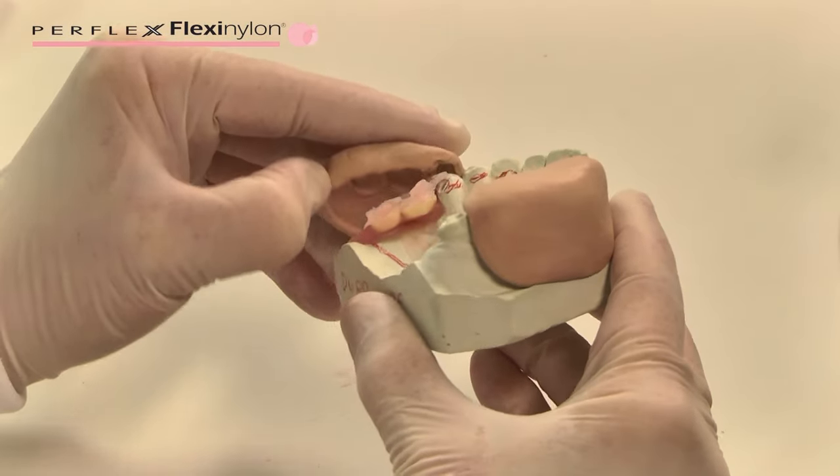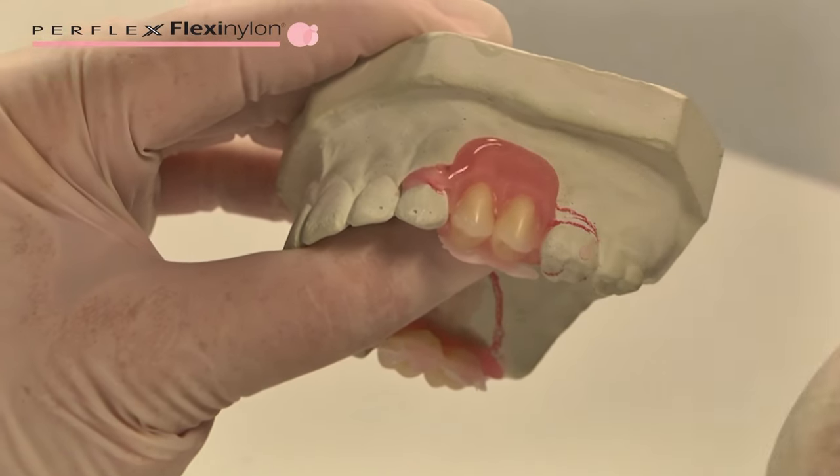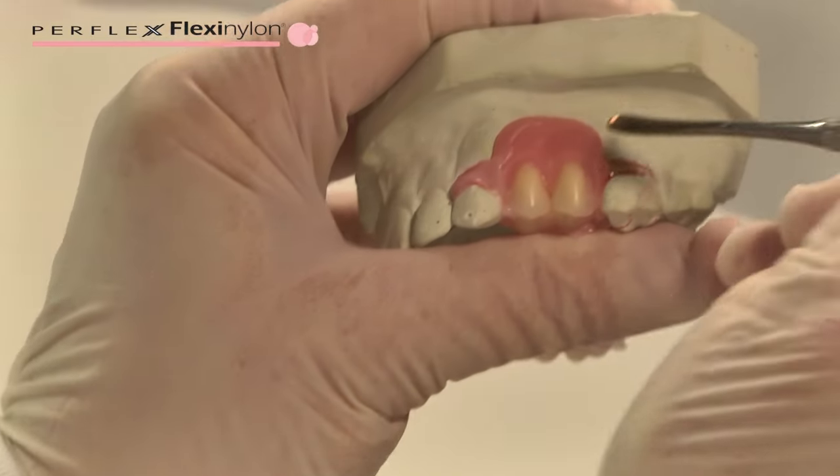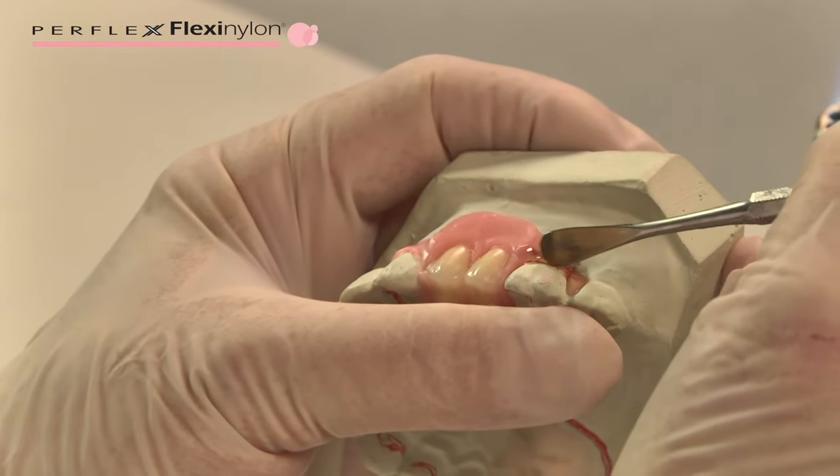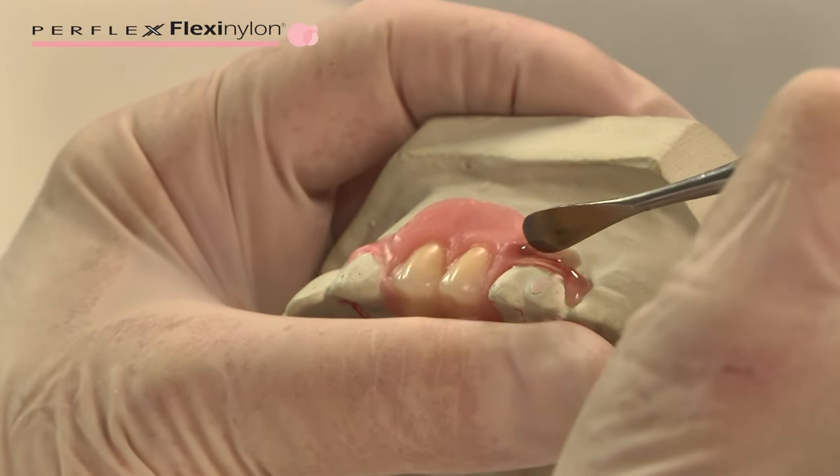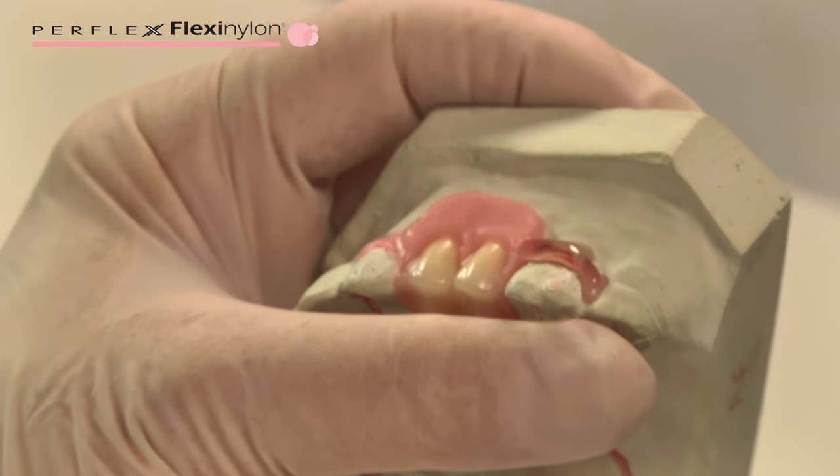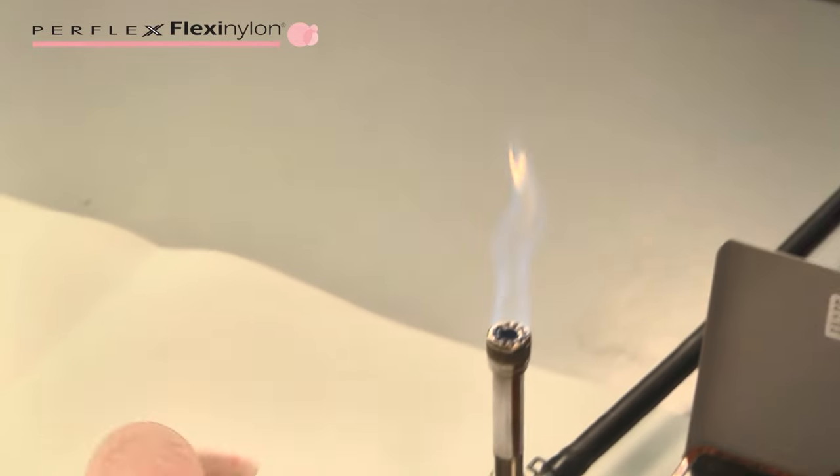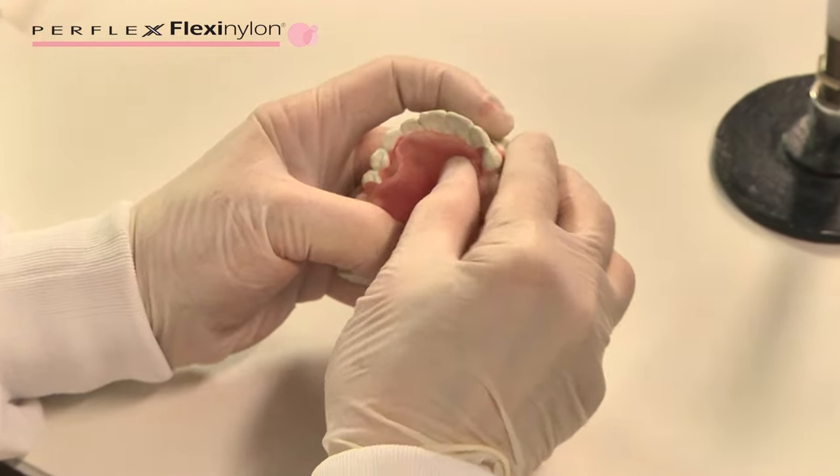Flexi-nylon waxing partial denture: Model the denture and the clasps thinner than for acrylic dentures. Flexi-nylon flexible nylon-type thermoplastic material can be designed with a typical design for flexible dentures or conventional dentures. Clasp thickness: 1.2 millimeters, 3 to 5 millimeters high, and the final thickness of the denture after polishing should be not less than 1 to 1.5 millimeters. Use prefabricated forms as palatal wax form. Keep thickness uniform. Keep anatomy natural.